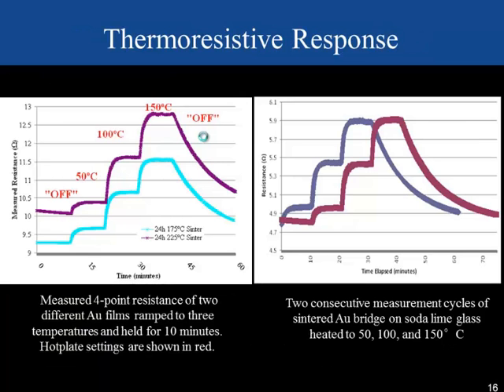So just to show the response of some of our samples, you can see in red here are the various set points of our heater, and each time it's held for 10 minutes. And you see for both of these sintered films, as it heats up, it rapidly rises and is very stable at each point, where the change is limited by the hot plate used in this experiment. Stability was also of interest, so this was repeated on multiple cycles. If we take the same sample here, we can place the same sample on 2 different cycles, and you see that there's no appreciable drift.